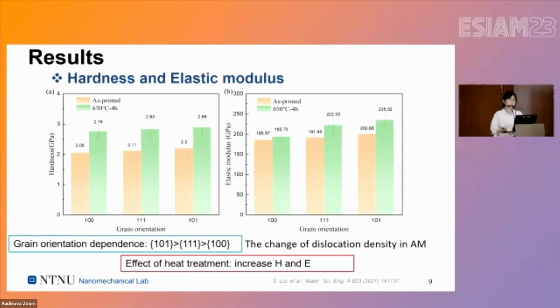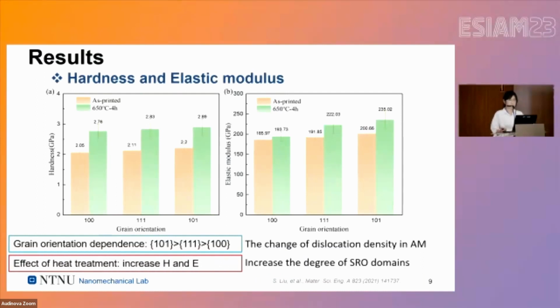And if we compare the results between the two samples, we found that the heat treatment can increase the hardness and elastic modulus. That might be because of the increase of the degree of short range order domains during the heat treatment.